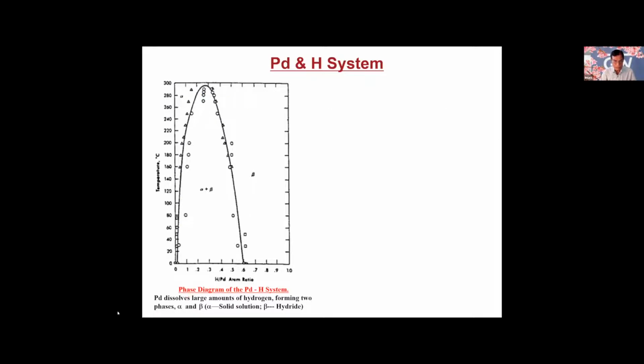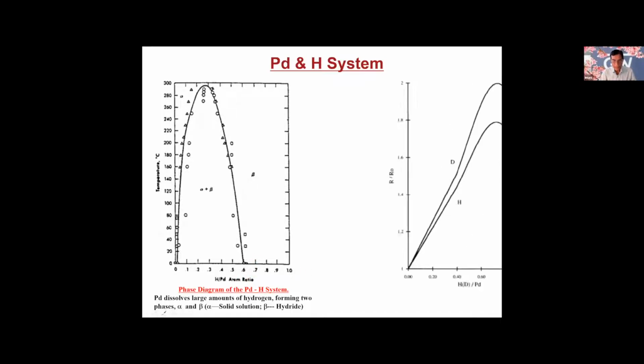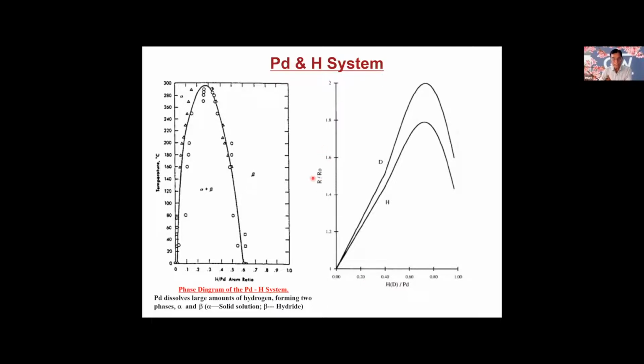Moving forward, this is the phase diagram of palladium hydrogen. And here you can see that this is the alpha phase here. This is a mixture of alpha and beta. This is beta phase. And alpha is the solution of hydrogen into the metal, and beta is the hydride. And if you look at some of the resistance, which normally we measure in experiments, this is hydrogen going into the metal, palladium, and this is the deuterium going in. You can see the resistivity at this point, you have an inflection. So this will be helpful when we do this experimentation and make the measurement for the resistivity or resistance.